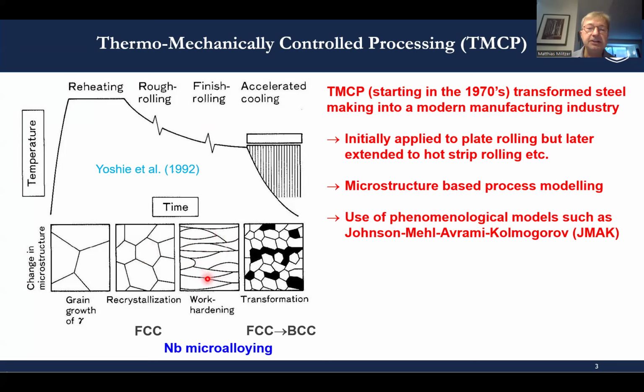And this has been facilitated primarily by microalloying with niobium. So I think it was in the 1960s that niobium became readily available as an alloying element for steels. And this pancaked austenite is a very good austenite conditioning for subsequent phase transformation on a runout table where austenite decomposes into ferrite or other transformation products. And this is now increasingly done by what we call accelerated cooling, so pressurized water sprays are being used, etc. And this has become a key technology in processing of plate steels, and similarly also in a hot strip mill.